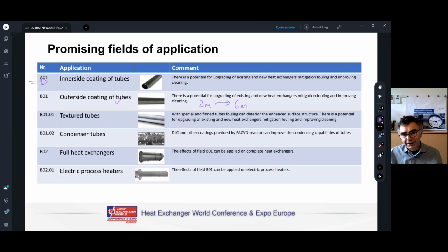Then to coat full heat exchangers would be nice, but the tubes are already too dense, so we cannot make this really work. We have to go this way at B01, B02. I think it will not work. We have too many tubes and too small gaps for plasma operation. Another thing is electric process heaters. They normally have not so many tubes and wider spacing. It depends on the application, of course, but there are standard applications which could be interesting.